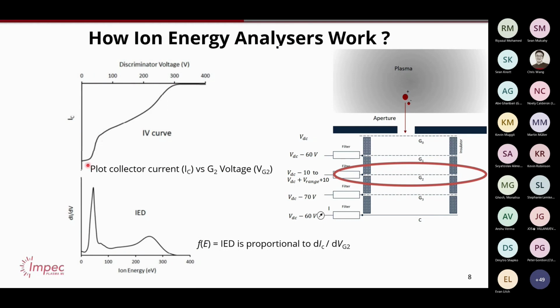So by doing the first derivative of this curve here, you get what's called the ion energy distribution function. So this is how many ions are present at what energies. Now this discriminator voltage, 100 volts, is representing an ion with charge 1 having an energy of 100 eV. And this is a fairly typical distribution. Well, there are many distributions depending on the tool, but we'll get into that.